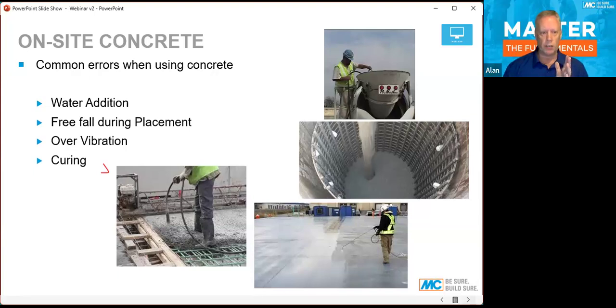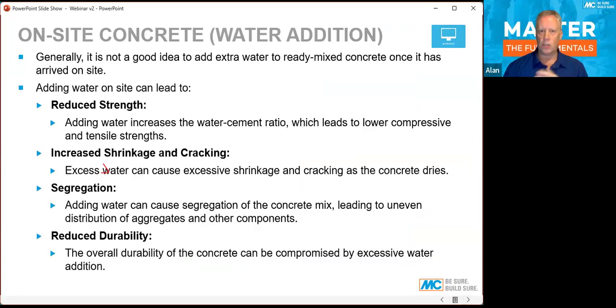So generally speaking, it's not a good idea to add water to the ready-mix concrete once it's arrived on site. The mix design should be done and trialed, as we said, so that the on-site performance doesn't need any adjusting. It shouldn't need any water adding. If it's not meeting site requirements, then we should adjust it at the batching plant, not at the site. So adding water can lead to a loss of strength, cracking, shrinkage, segregation, and of course reduced durability. Those are things that we don't want. We definitely don't want to see those things.